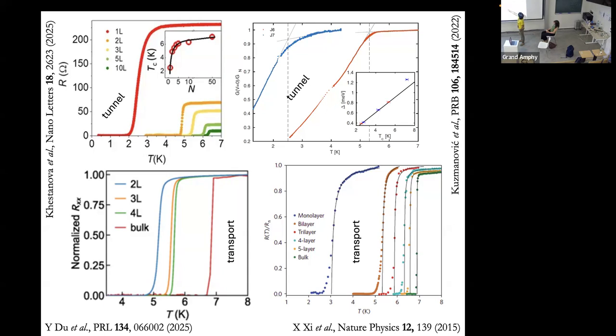But TC as a function of layer number is not aligning to what we're seeing here. I think this may not be the right picture because it looks like transport, not like tunnel. I think I took the wrong picture, so I have to look for it. I'm sorry about that. But they got very much lower numbers. This is some of our stuff, and you can see the numbers are even lower because this is 6 layer, and this is 2 layer. It's the 2 things that we showed you.